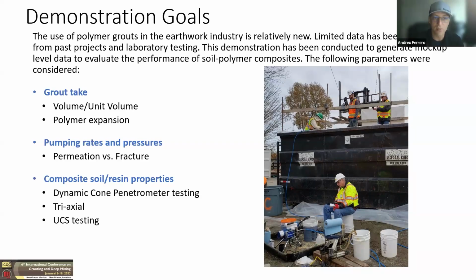We also looked at the composite soil resin properties. We did dynamic cone penetrometer testing in situ, and then we took some core samples of the treated materials, and we conducted triaxial, direct simple shear, and unconfined compressive strength testing.